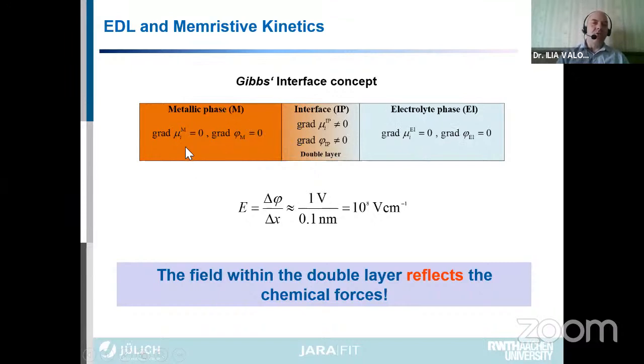Within the metallic phase, on the macroscopic level, you don't have any gradients. So you have constant chemical composition, you don't have a gradient of the electrical potential, everything is constant. But on the interface, exactly what happens at the site of the membrane of the neuron, you have a gradient of the chemical potential. This is usually the concentration, and you have a gradient to compensate this. You have a gradient of the electrical potential. So in fact, the field which is generated within this electrical double layer is reflecting the chemical forces on both sides. And the fields that are generated here are in the range of 10 to the 8 volts per centimeter.